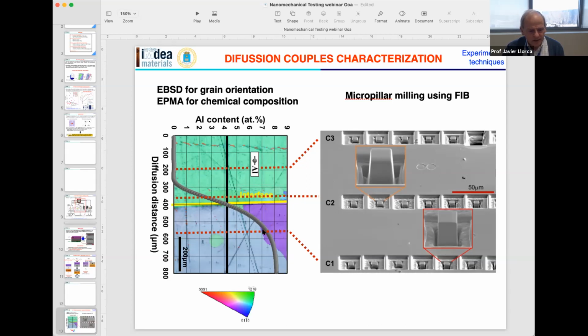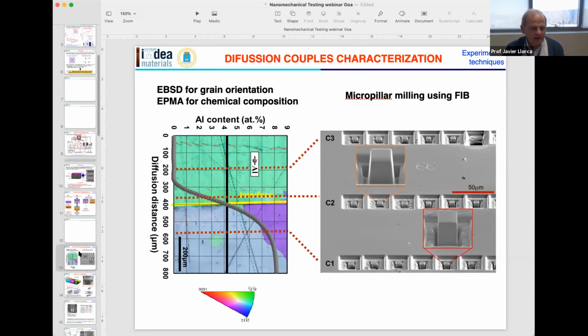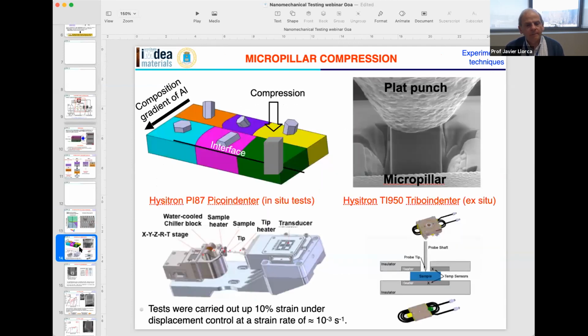If you do that in this grain here, then you have grains with different orientation. So in this way, you can have micropillars with different aluminum content and also with different orientation to activate different deformation modes. So this is the next step. At the end of the day, this is your diffusion couple. You have different grains, and in these different grains you can have different orientations. You can extract micropillars. You are always going to compress perpendicular to the surface. This is the final setup.